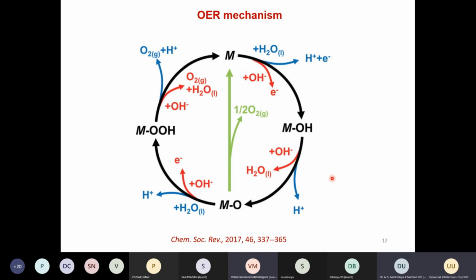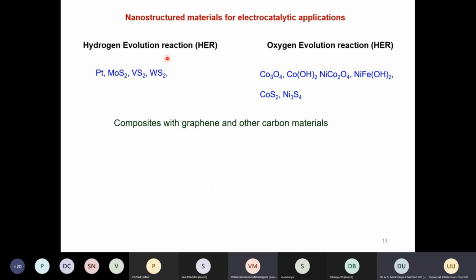That's why, compared to the hydrogen evolution reaction, there are more research reports on the oxygen evolution reaction, on how to develop a suitable catalyst which can do this oxygen evolution process efficiently. There are various catalysts. As I mentioned before, platinum is one of the best catalysts for the hydrogen evolution reaction. Of course, molybdenum sulfide and other 2D transition metal dichalcogenides like vanadium sulfide and tungsten sulfide are very good materials for hydrogen evolution reaction. On the other hand, for the oxygen evolution reaction, mostly cobalt and nickel based materials are very effective. For example, cobalt oxide, hydroxide, nickel cobalt oxide like the spinel structures, and hydroxides and sulfides; various catalysts have been developed.